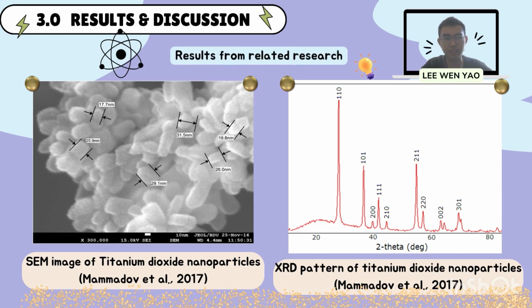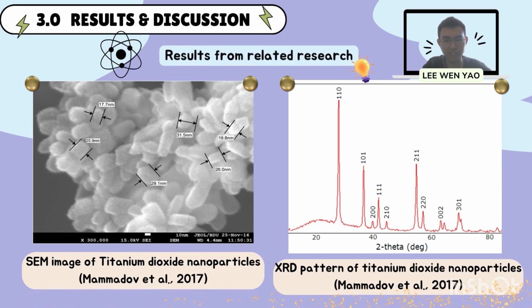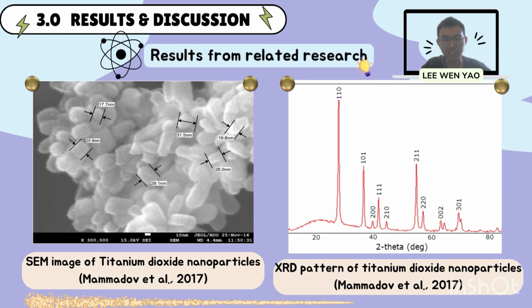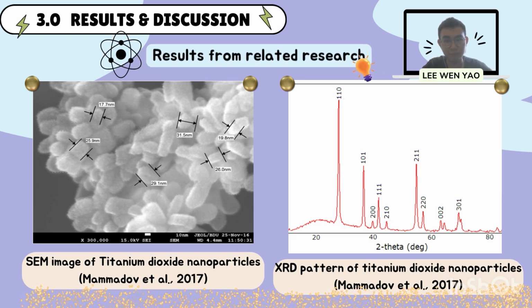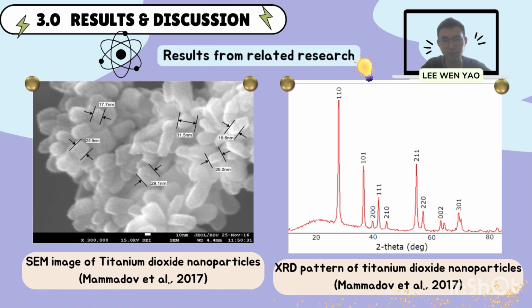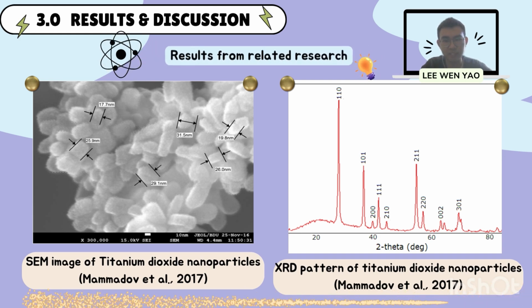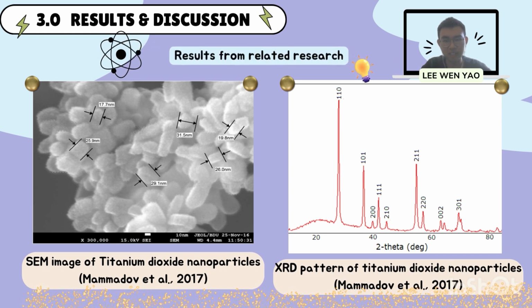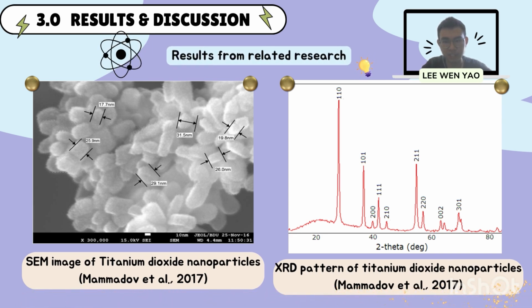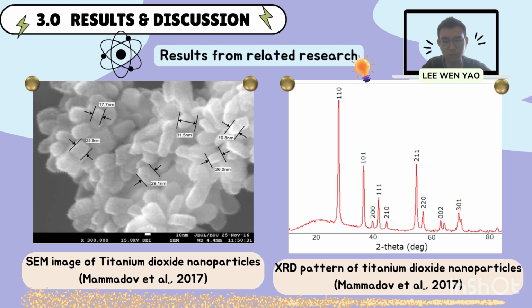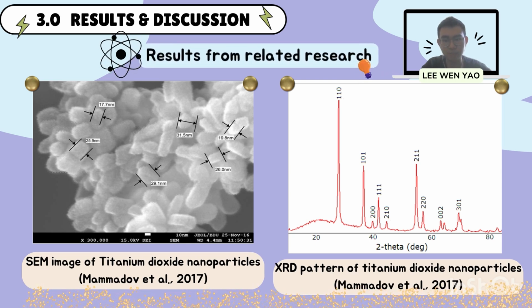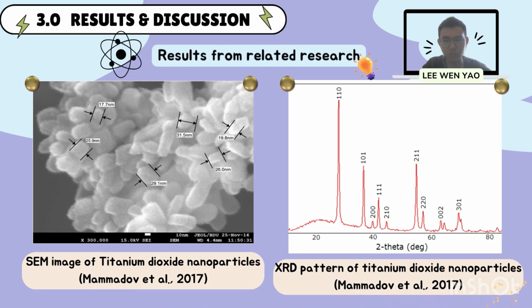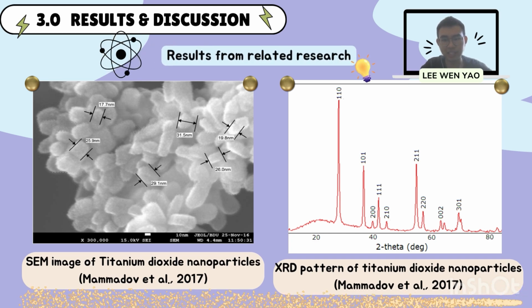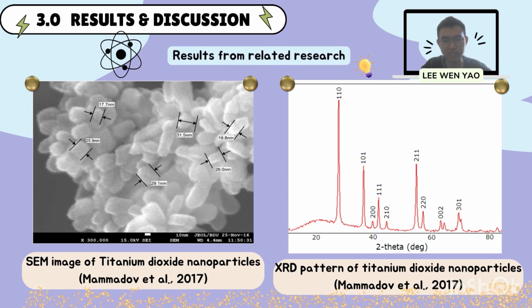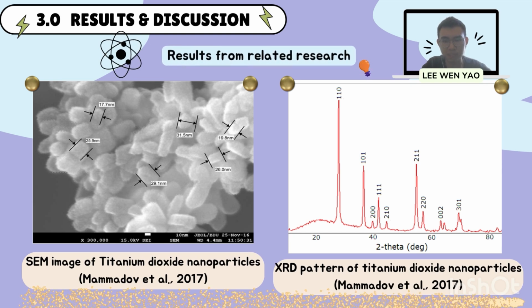Hello, my name is Lee Wen Yao and I will discuss the results and discussion in this assignment. The pictures below show the titanium dioxide nanoparticles synthesized by Mammadov and others in their investigation during 2017. In the SEM image, it is clearly seen that the nanoparticles produced were homogeneous and had diameters around 15 to 30 nanometers. Purity and crystalline properties of nanoparticles were investigated through XRD. All of the XRD lines indicate that the crystal is in rutile phase and its average size is 18 nanometers based on the 110 peak.